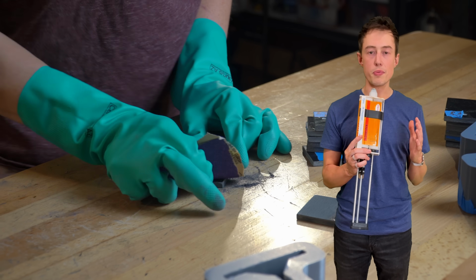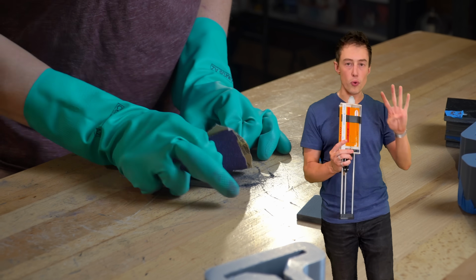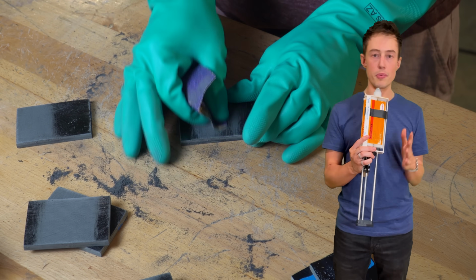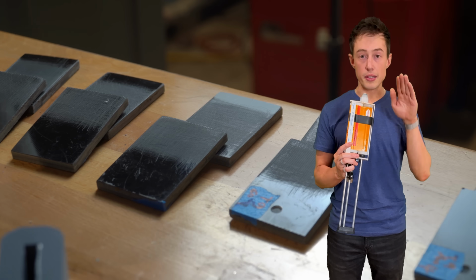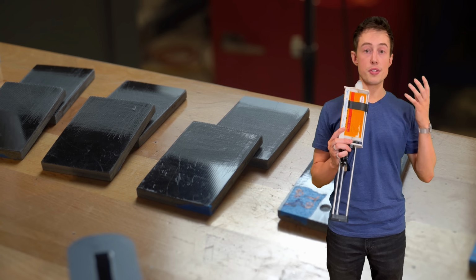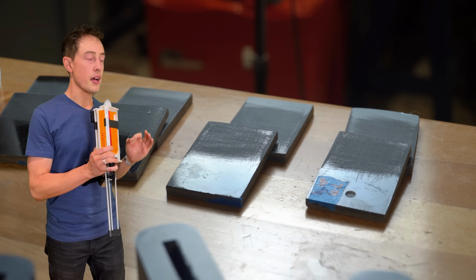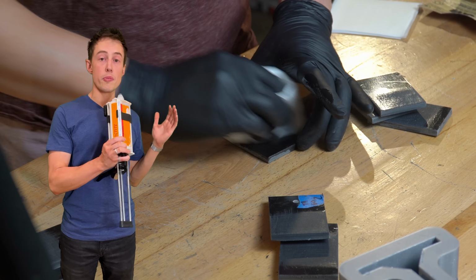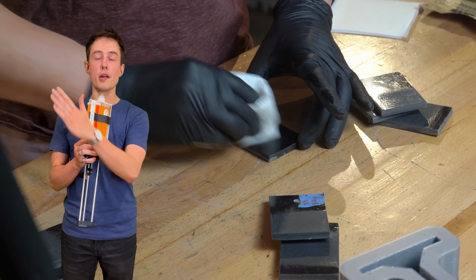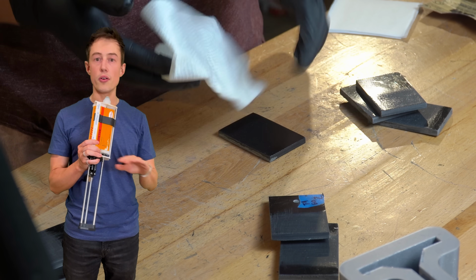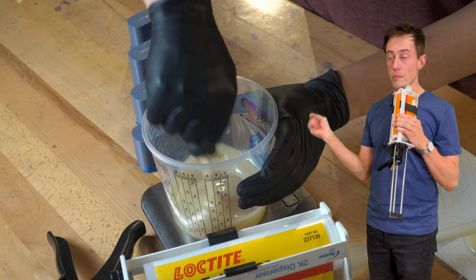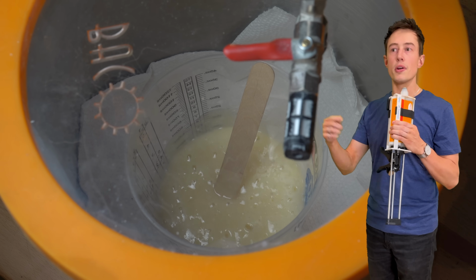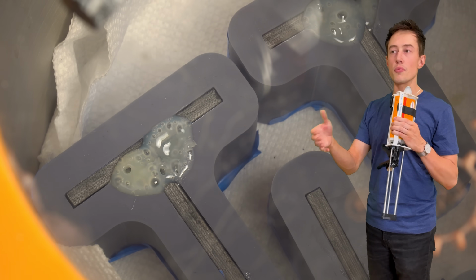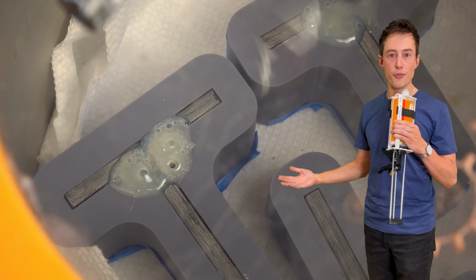Finally, we should compare this with some sanding. So I hand sanded 4 more coupons with 60 grit sandpaper. I did this with moderate strength, linearly, mostly back and forth until the surface was gray. Then, after sanding, I cleaned that surface with acetone for about 10 seconds, then came in with IPA and wiped it off just like all the other samples. And for the epoxy, I mixed it up in a cup, degassed the cup, poured the epoxy into the mold, and then re-degassed the mold before letting it cure for 48 hours.